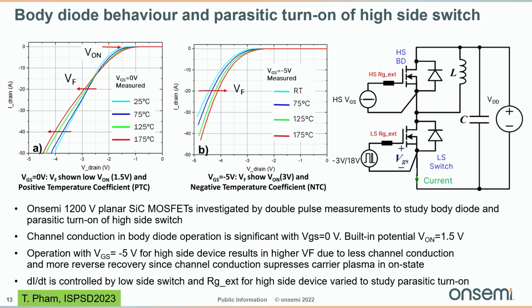In the center, we have applied -5 volt to the gate, and then we have the regular 2.8 volt or so built-in potential. And it's interesting that the operation with VGS 0 volt has some benefits. As you can see, due to the channel conduction, we can have a lower forward voltage drop. And another benefit is that due to the channel conduction, we bypass the PN junction, and therefore we get less carrier plasma in the on state. So we can also improve the reverse recovery characteristics.